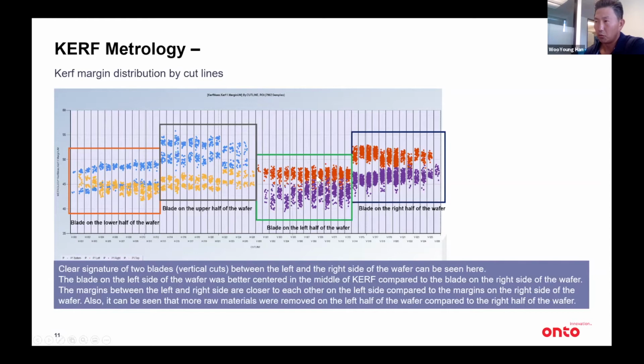Also, if you add the margin on both sides, you can see the left half. Actually, in this case, the right half is larger, indicating less material has been removed on the right half of the wafer. So maybe this is indicating the blade may be going deeper on the left half of the wafer, removing more, creating more debris, and then removing more materials, right? So these are all things that are very important to prevent cracks and chippings from happening at all in the first place.